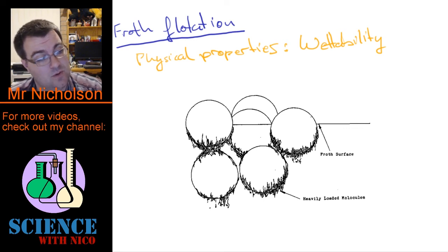And you may have to modify its surface. In the case of mineral sulfides such as galena, sphalerite, chalcopyrite, you can often use a xanthate, a class of molecules known as xanthates, to make the surface not like water and make it like the bubbles, and that results in it quite readily attaching to those bubbles. And it's as simple as skimming or directing those bubbles down a launder to separate them off and concentrate your mineral. It's a really elegant system, and a really nice one to finish on.